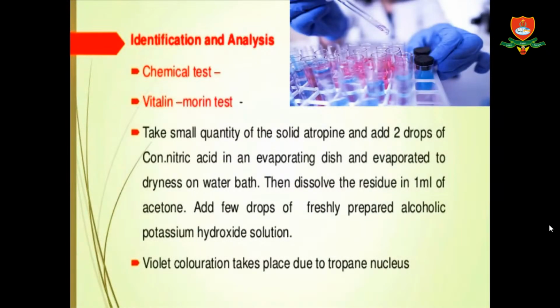Okay, so there are many alkaloids. For the detection of the atropine alkaloid, the chemical test is done: the Vitali-Morin test. We took a small quantity of solid atropine and added concentrated nitric acid in an evaporating dish, and kept it in the water bath. Then we added 1 ml of acetone and a freshly prepared potassium hydroxide solution. Thus the violet coloration takes place. This indicates the presence of atropine.